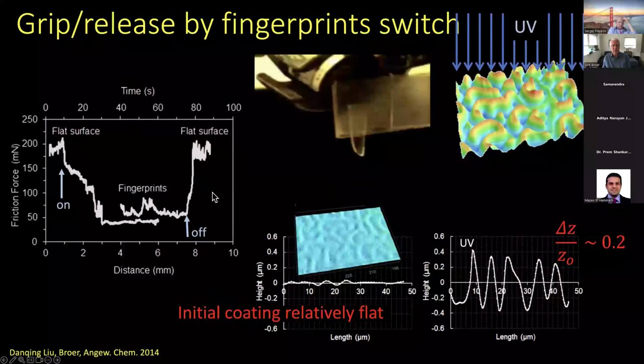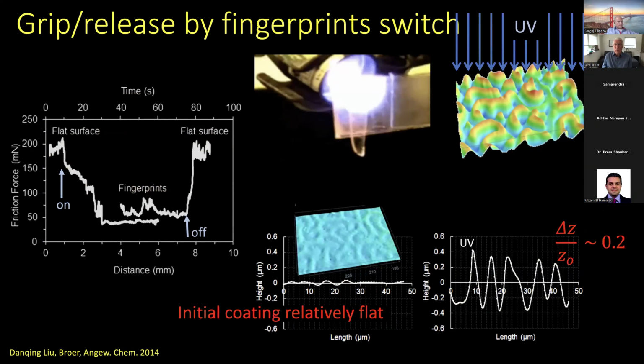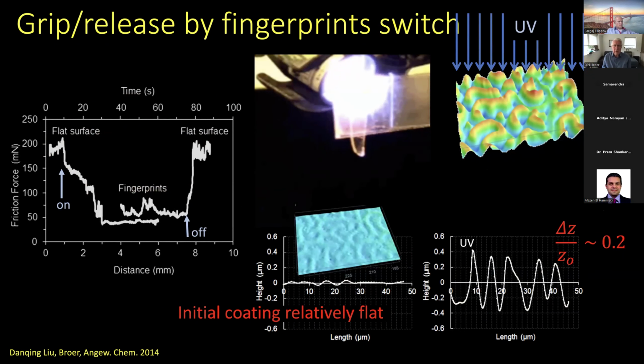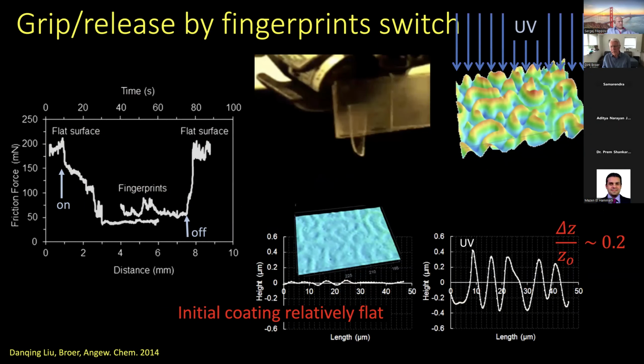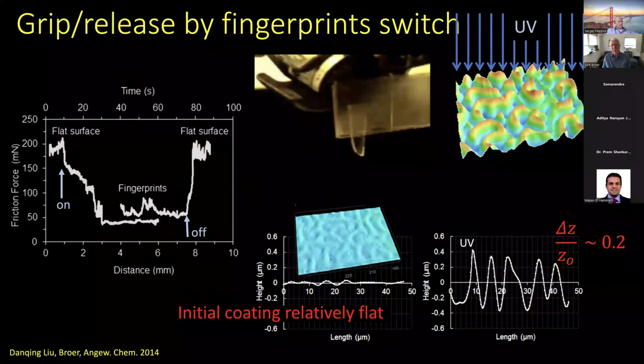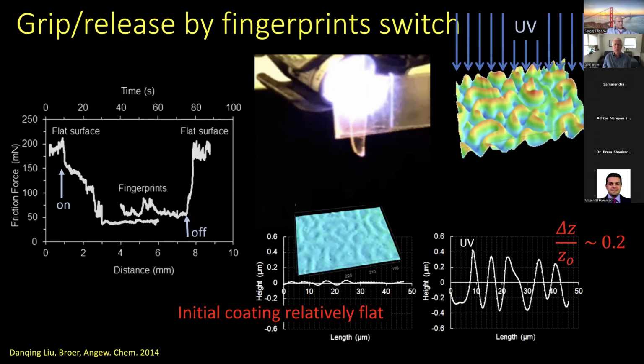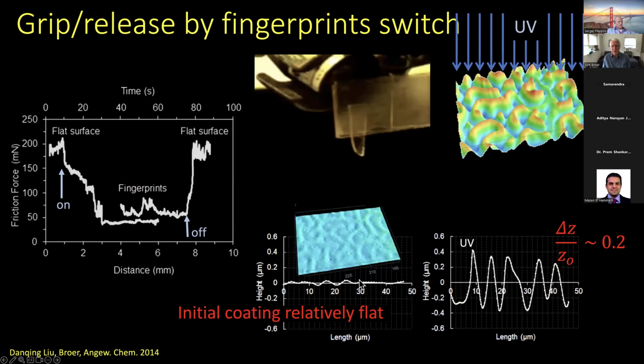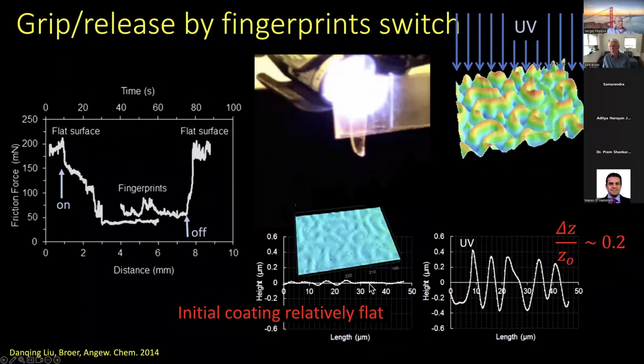down in this case. And this, of course, leads to many different properties, but one of the properties is the change in friction coefficient, which could, for instance, be used as a gripper. This figure again shows the change in height. This is in the flat state, a little bit of Marangoni. This is in the actuator state, where you have a high surface profile.